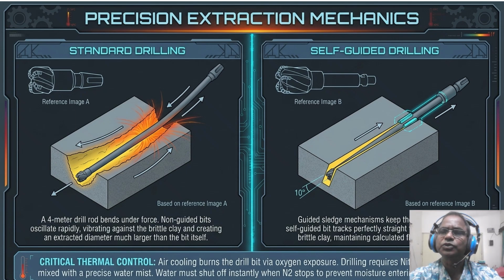Look at the critical thermal control note at the bottom. We use nitrogen cooling mixed with a precise water mist to save the bit from oxygen exposure. However, the water must shut off instantly when the nitrogen stops. So, what is the factor? If moisture enters the taphole, it reacts with the hot metal, causing a steam-driven blowout that can destroy the taphole face and injure the crew. We are drilling for a calculated diameter to ensure a predictable cast duration. The quality of that drill path and the clay's wear resistance determine the shape of your cast curve.